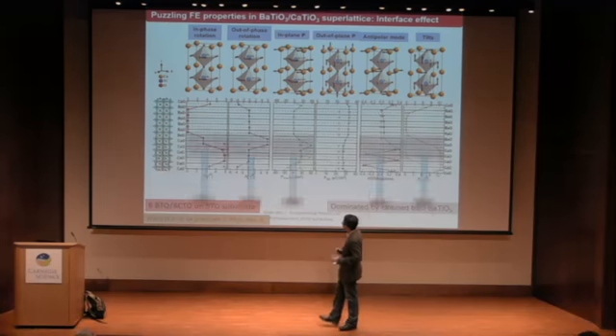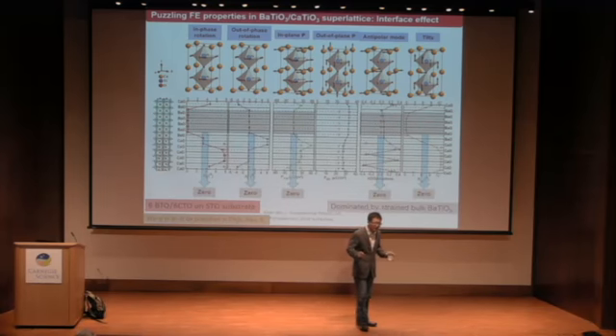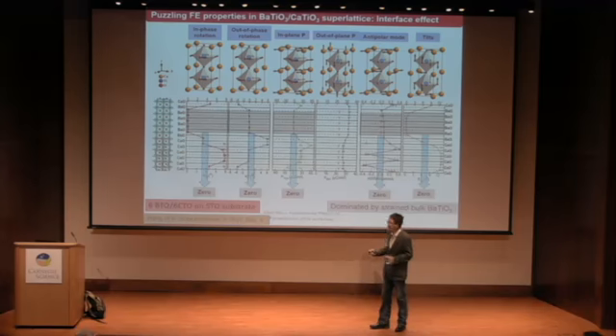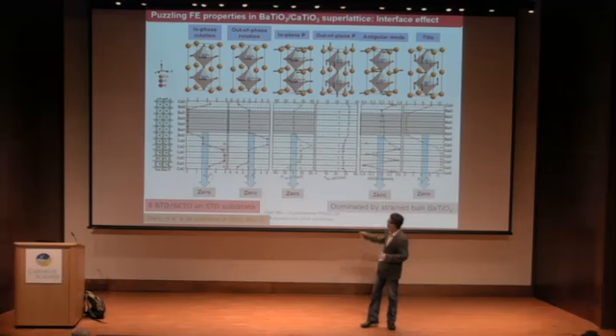Then we look at the bulk region of barium titanate. It's very boring and also very interesting, clear. It's dominated by the bulk effect of barium titanate. You see no distortions along the 110 direction, no octahedral distortions, and okay.